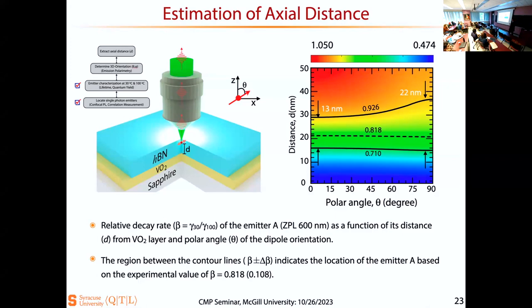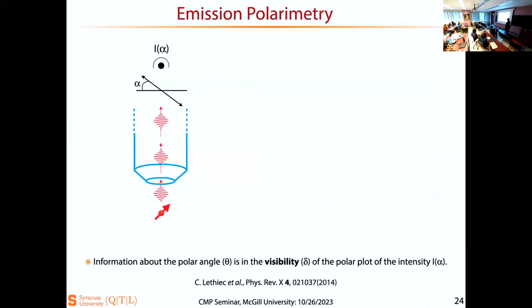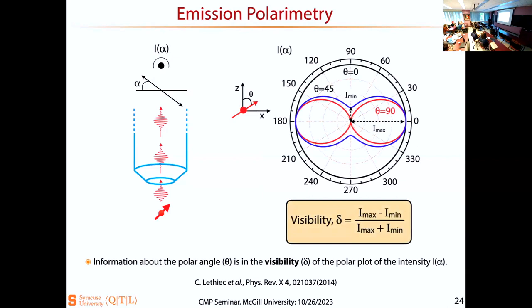We also really wanted to measure the polar angle. So I spent a lot of time really understanding one of the papers here, in which we perform emission polarimetry. What that means is you collect the light from a dipole and change the polarization in the collection pattern to see what the emission looks like. Depending upon whether the dipole is in plane or out of plane, it looks like a dumbbell, or if it is out of plane, it looks very isotropic.